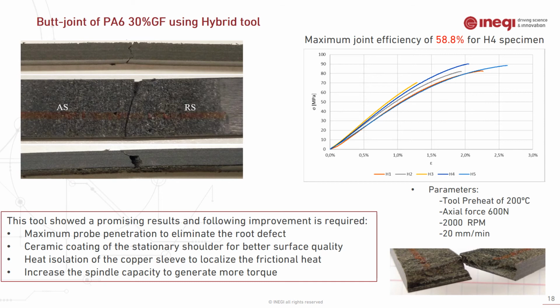As I mentioned before, the range of the parameter that could be tested using the available tool and the machine was narrow. However, we could manage to use those parameters for testing and welding the plates, but we preheated the tool up to 200 degrees instead of dwelling for a long time. Also kept axial force at 600 Newton, RPM 2000 and welding speed of 20 millimeter per minute. You can see the 5 specimens that were produced and tested, and all of them broke at the retreating side of the weld. In general, this tool showed a promising result, and the following improvements are required for further investigation.